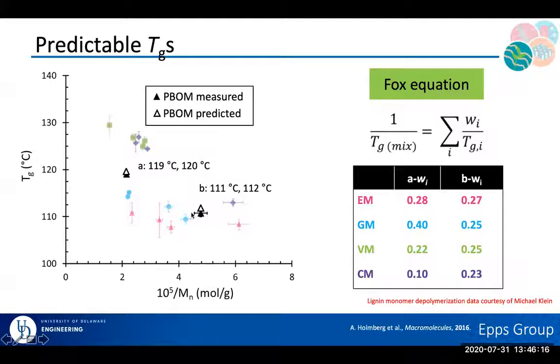So one of the nice things is we got really nice agreement between our predictions and our measured data. I will say that this is some of our best case data, though our worst case data seems to be off by no more than 5 or 6 degrees Celsius, which is still really good when we're thinking about application potential and predicted application potential.